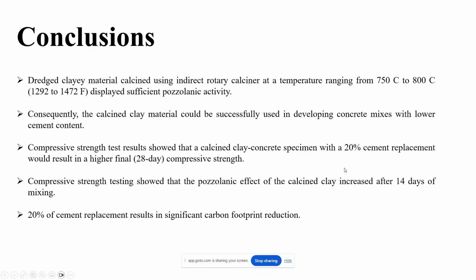The optimum range suggested is 20% cement replacement, which basically results in a similar or very high 28-day final compressive strength. And that 20%, considering how much concrete we're using and how much cement we're going to save, will basically result in a significant carbon footprint reduction.